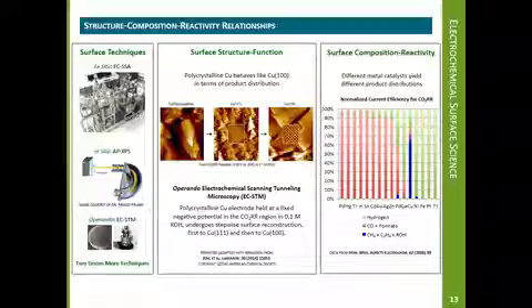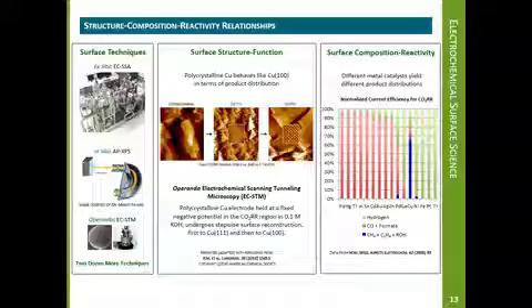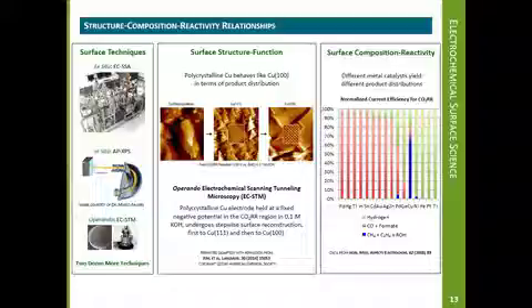An example of the dependence of catalytic function on surface structure is given by the reduction of carbon dioxide on copper. A copper surface that nominally exhibits a mixture of atomic regions possessing hexagonal and square orientations was observed to reduce CO2 to the same reaction products as a monocrystalline surface exhibiting square domains only. This phenomenon cannot be explained by surface composition alone.